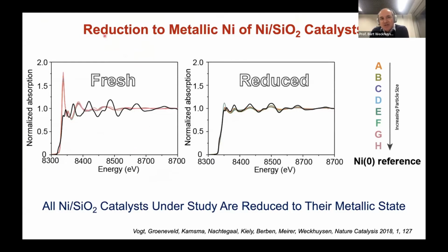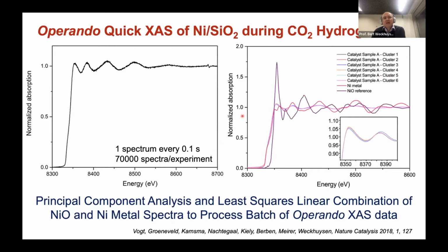Let's first see what happens during the reduction in hydrogen. This is fresh, this is reduced, and here I show you the different metal nanoparticle sizes of nickel on a silica support. All of them reduced to the metallic state. Now, more interesting is what happens during CO2 hydrogenation. So what we did is we actually have been measuring the changes happening during this process. We have also been making pulses of hydrogen, CO2, hydrogen, CO2. Now, important is that you can now do a cluster analysis. I come later on to that. And you can also measure the nickel metal and the nickel oxide references. You can see then how it changes from the metal to nickel oxide and the relative contributions of these different species of metal and metal oxide species.